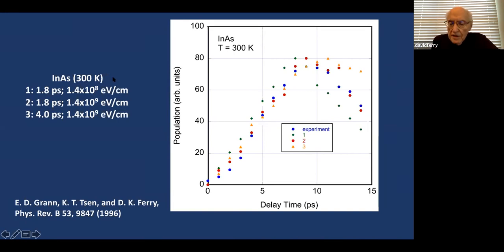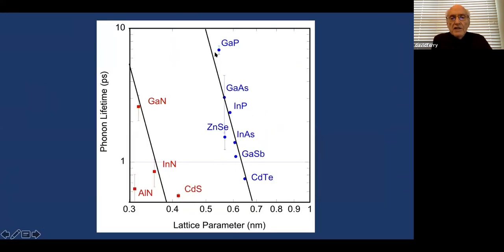But we can get these values for a lot of materials, and it turns out they have some common characteristics. All right, so here's a lot of materials: gallium phosphide, gallium arsenide, indium phosphide, indium arsenide, gallium antimonide, cadmium telluride, zinc selenide. All these blue are zinc blende materials. The gallium nitride, indium nitride, aluminum nitride, cadmium sulfide, those are all wurtzite materials. And I'll explain that a little more later.